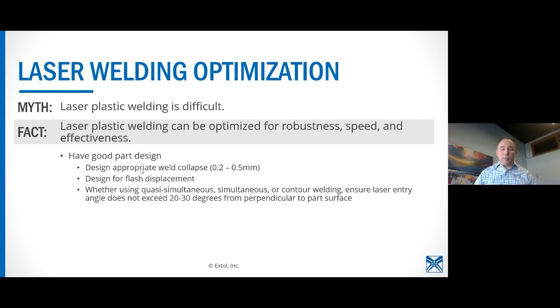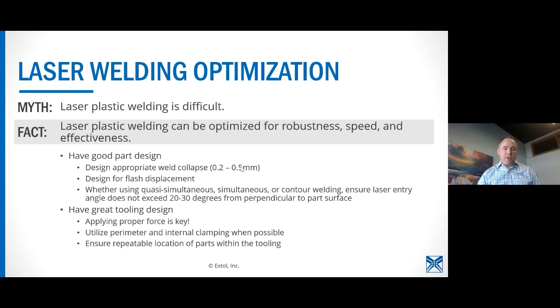And whether you're using any three of those, making sure the laser entry angle does not exceed 20 degrees, sometimes up to 30 degrees from perpendicular to the surface matters. What that means is you just need to make sure you have a clean entry as perpendicular to that transmissive layer as possible. Otherwise, you can get some refraction off of that if that angle is too steep.